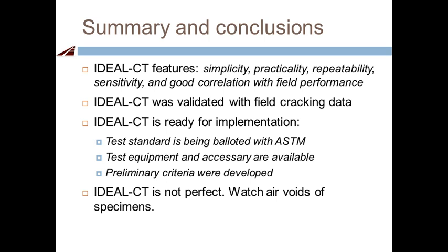It really depends on the requirement for your overlay test. In Texas we have different requirements for different mix types. It's really up to the DOT to set up criteria based on their mix type and environment. If you're in a cold area, you may need a threshold of 150 rather than 100.